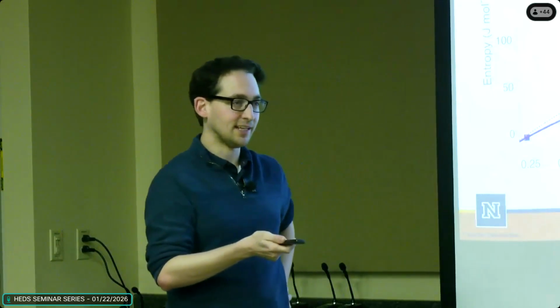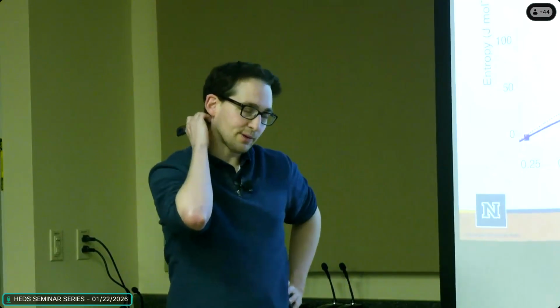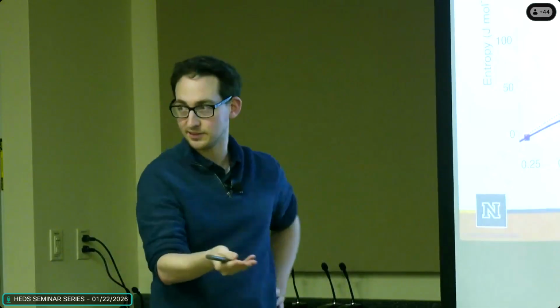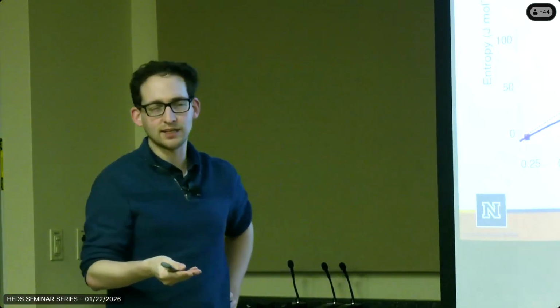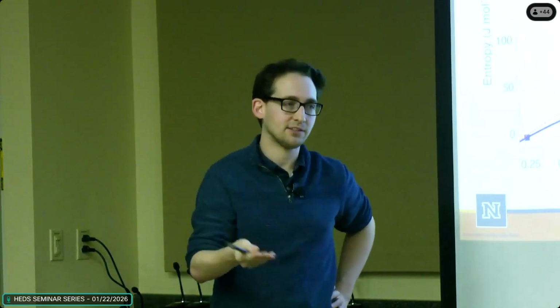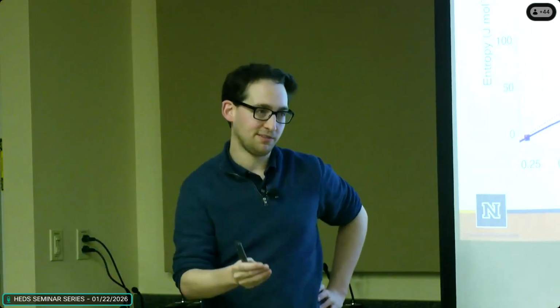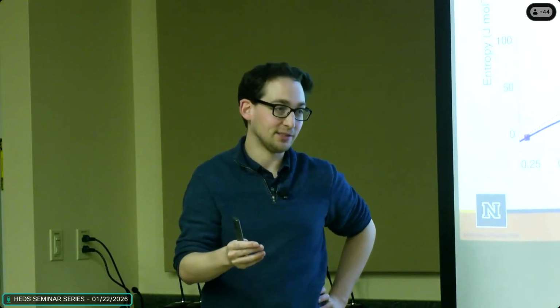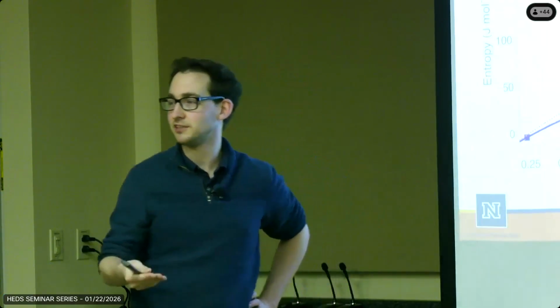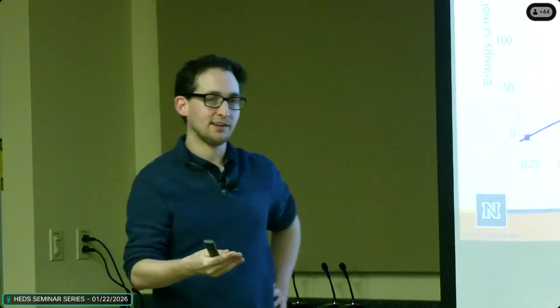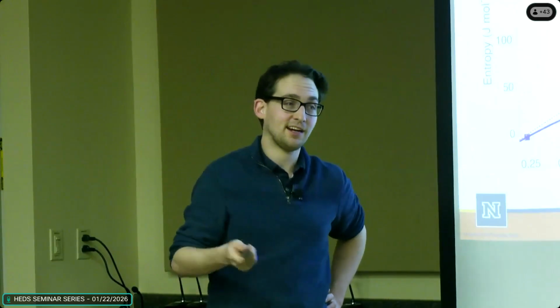And one of the problems is that it rapidly expands at this late time. I can't answer that experimentally because you cannot stop, right? Our heating process is the electrons. The electrons are dumping energy into the ions. So already it's slightly different from equilibrium thermodynamics, in that we have a non-equilibrium system with hot electrons and cold ions. And you cannot turn off the heating of the electrons just before the superheated state. We cannot say, okay, now the electrons are going to stop dumping their energy into the ions just before it melts. So experimentally, there's no way to do that. So it's a good question, and I don't know.